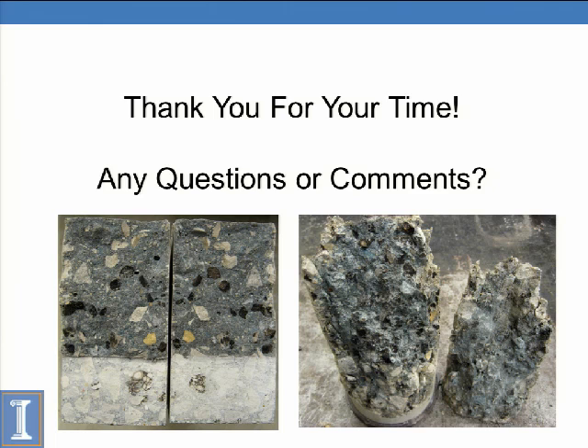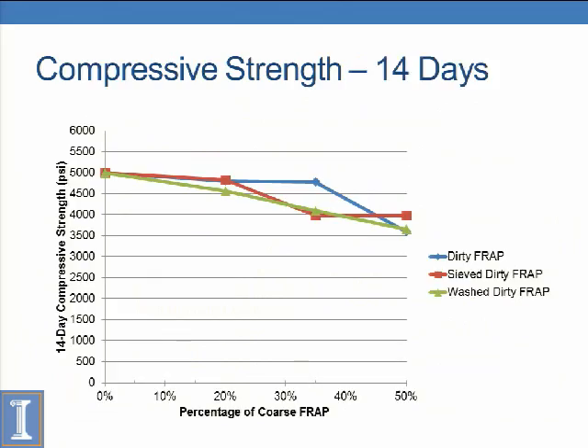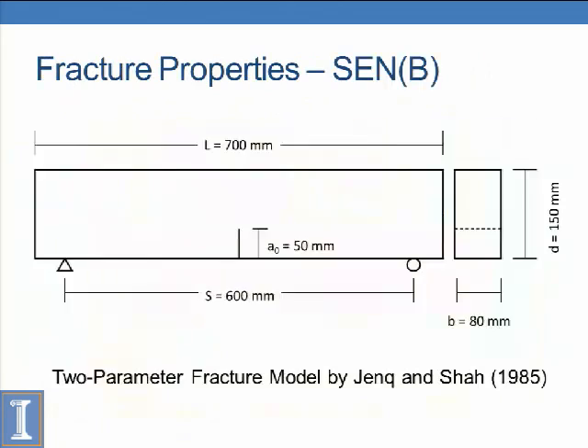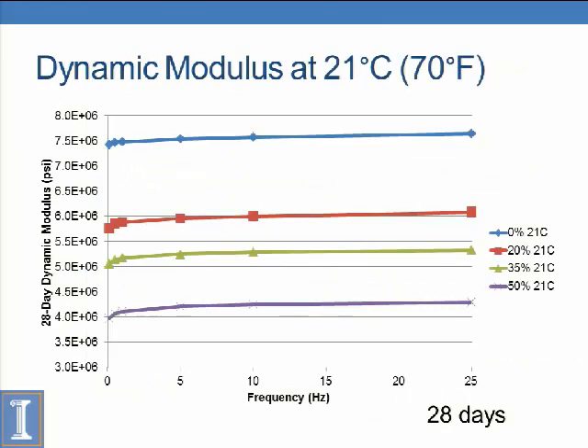It was a very nice presentation, thanks. Thank you. But one thing I noticed, none of the material properties was really compromised except modulus. And you've shown some results at 21C, and almost half of the modulus reduction as you go to 50% RAP. I'd assume this reduction would be even higher if you go to higher temperatures. You said you would study creep next. So do you conclude that from this, for example, modulus results, deflection problem will be the most critical criteria for using RAP in slabs?